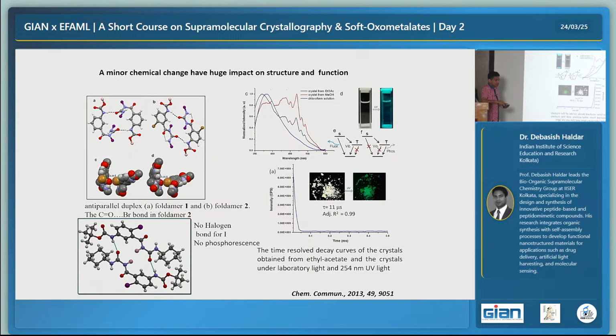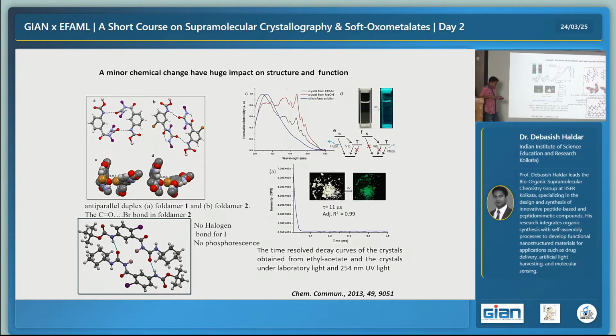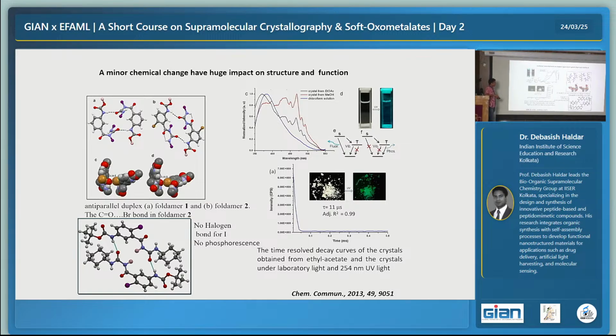We developed this compound with meta-aminobenzoic acid and N,N-dicyclohexyl urea. The compound formed a duplex stabilized by intermolecular hydrogen bonds, and then we replaced one of the hydrogens with a bromine, a heavy atom. What we figured out is that with bromine there is now a C=O···Br halogen bond, and due to that halogen bond and heavy atom effect, the compound is now showing phosphorescence.